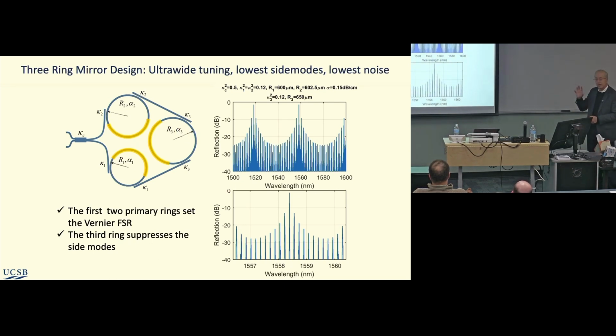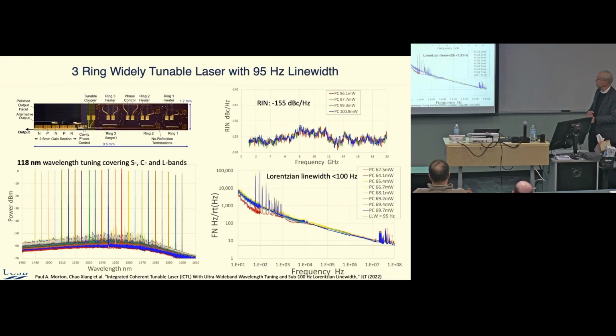You can do better with 3 rings. This is a picture of what that looks like, and you can get better suppression of these close-in modes, and push these further out. The end result is you get wider tunability and narrower line width as well, shown here. This is a picture of what the device actually looks like. The 3 rings are a little hard to see, but it's not too big.